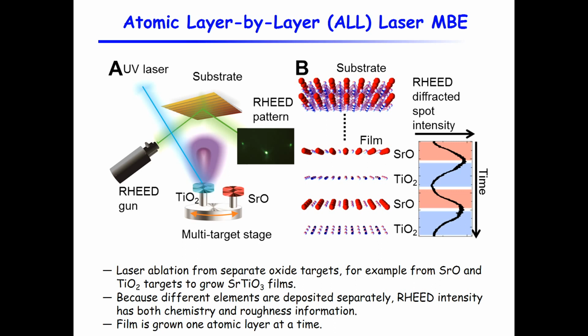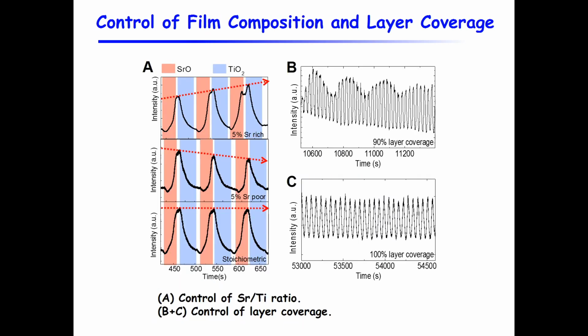Yes. What's the time scale for this oscillation? Well, you will see that in these slides. Here are seconds. We use a 1 or 2 hertz pulse rate, and it takes about 100 pulses to grow one atomic layer. Roughly on the order of 100 laser pulses per atomic layer, and we run at 1 or 2 hertz repetition rate.